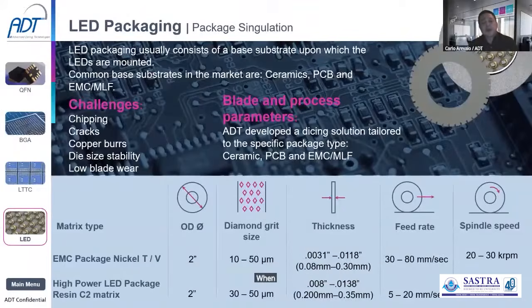When you're dicing a hard LED base substrate, then you're going to use a resin soft blade. The diamond grit range will be similar, 30 to 50 micron. Thickness would be within 200 to 350 micron. But if you're cutting with a resin blade on a hard base substrate, feed rates are going to be slower than usual. So the feed rate range for this hard substrate would be just 5 to 20 millimeter per second.